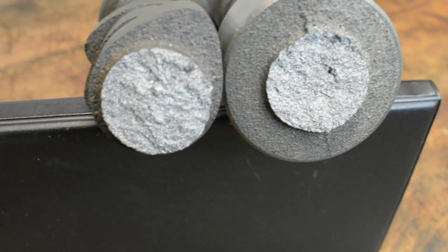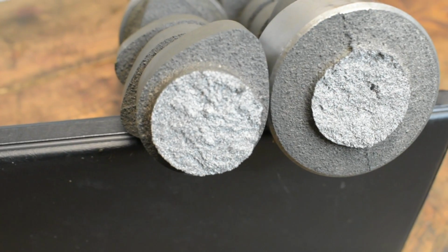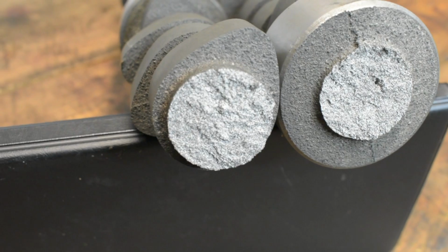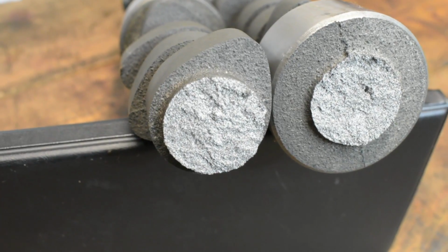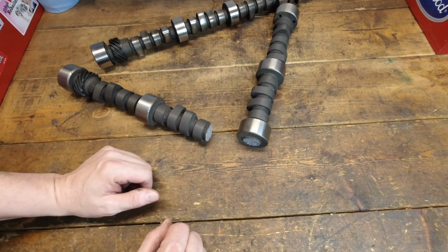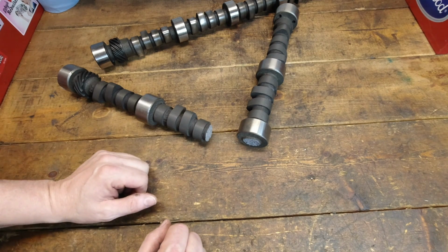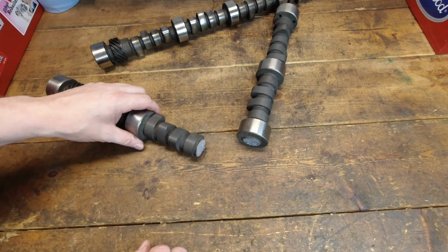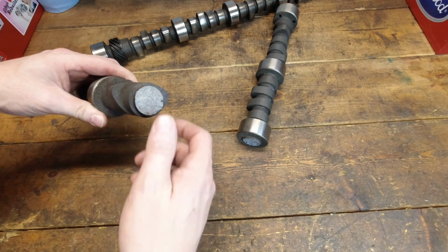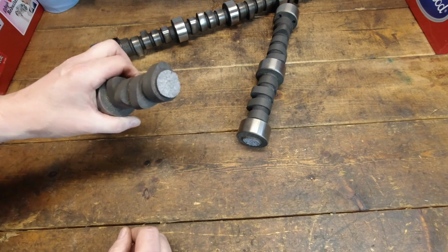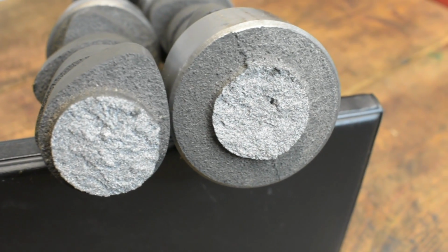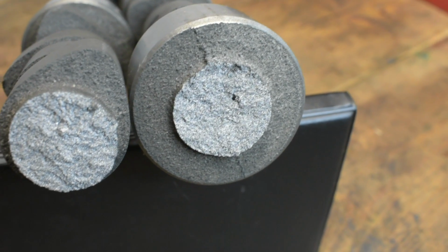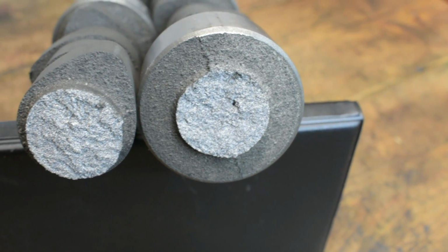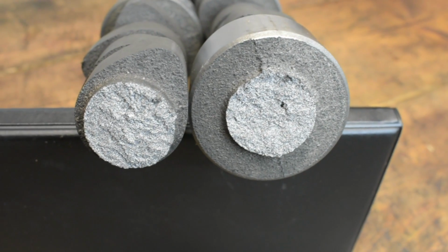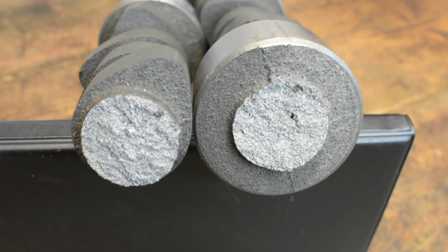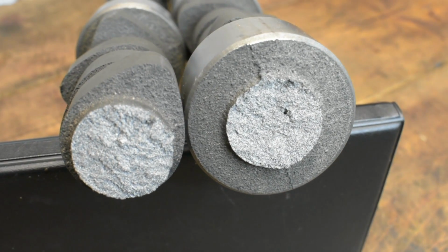They are extremely brittle. And you see that quite frequently, again, with folks complaining that they got a broken camshaft and they just assume that the manufacturer sent it out that way. And that was dropped from, I think, a height of about 3 feet here. And God only knows how FedEx and UPS treat these things. So it's certainly not going to get treated very well. That's why cam manufacturers are usually fairly picky about how they pack them, in a fairly heavy box and bagged, and keep them from sliding around in there. They'll put them in tubes, whatever it takes to keep these cast cam cores together.